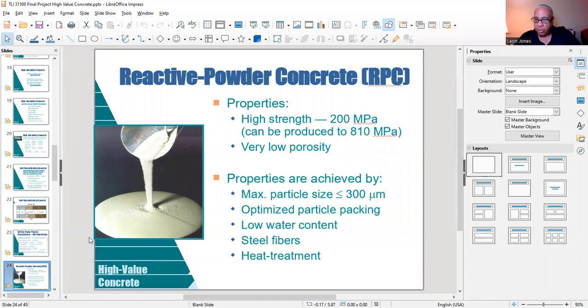Properties, RPC, high strength, 200 MPa, can produce to 800 MPa, very low porosity. Now, properties achieved by this type of concrete, you have a maximum particle size of basically under 300 micrometers. Optimized particle packing, low water content, steel fibers, heat treatment. This is what it looks like.